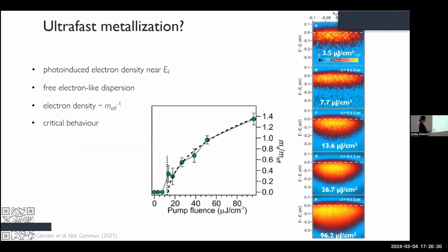We can do this also as a function of excitation density. So not only vary the electron density by just looking at the time-dependent electron density, but by exciting it sufficiently strongly. And you see that for low excitation densities, you keep on having a flat dispersion, while after a critical excitation density, you get this nice parabolic shape. And you can plot the inverse effective mass also as a function of pump fluence, and you get a very nice critical behavior as you would expect it for a real phase transition.